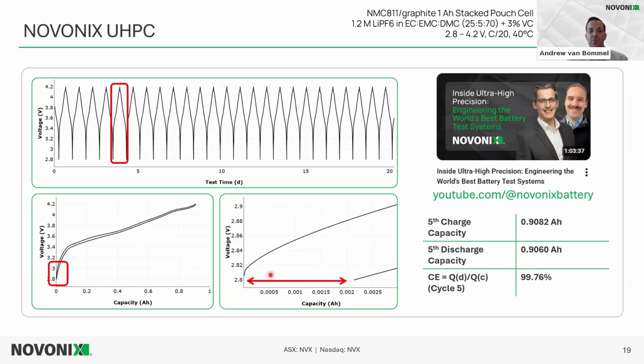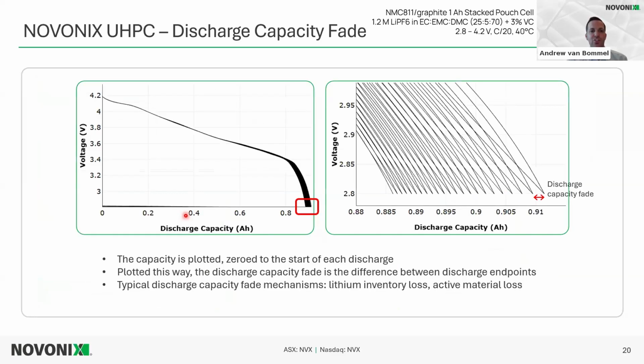There are a few reasons why this gap can exist. One could be that the charge keeps on moving to the right, so there are more oxidative processes that happen during the charge process. Another could be some degradation leading to the loss in discharge capacity. So I'm going to separate those out right away, rather than showing coulombic efficiency graphs, which is what we normally do. You can check some of the videos, and it'll be discussed in a different way as well.